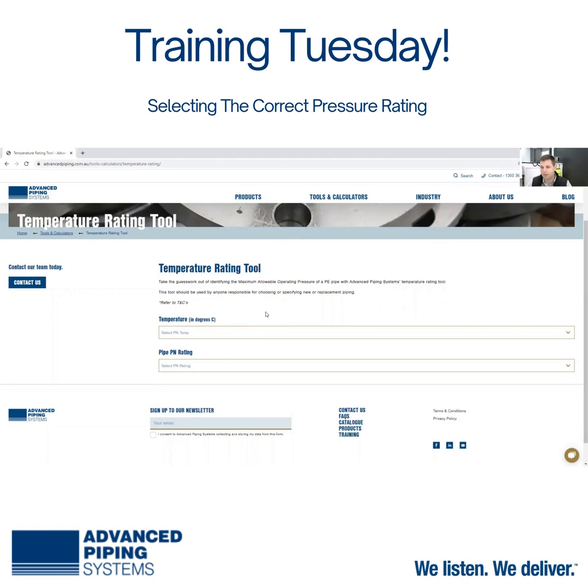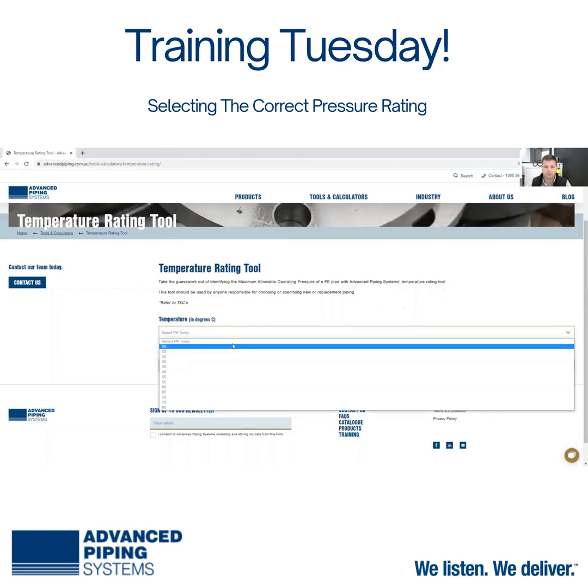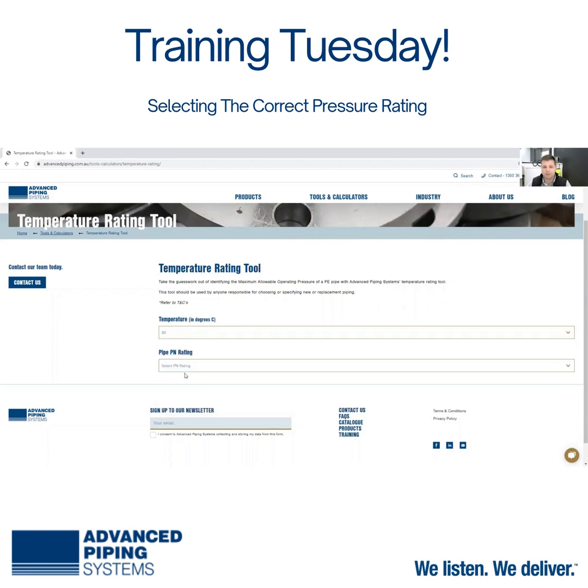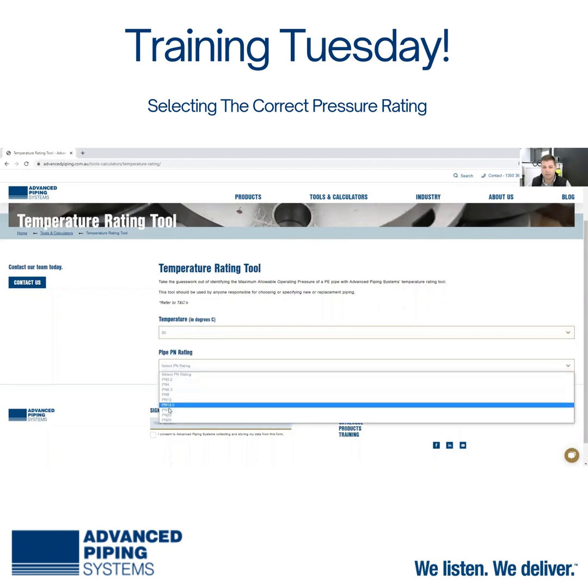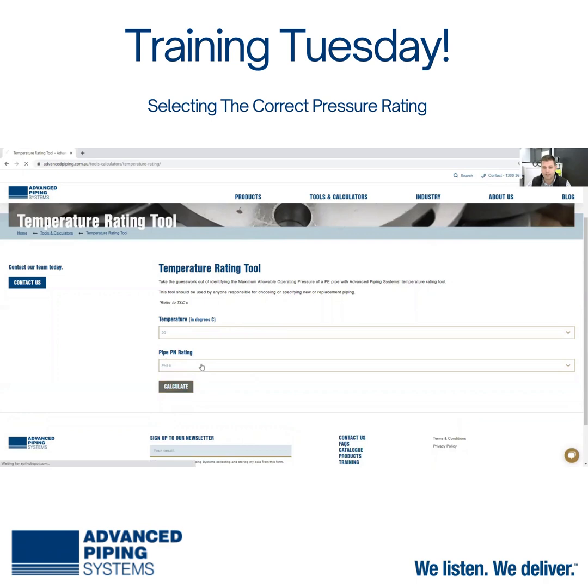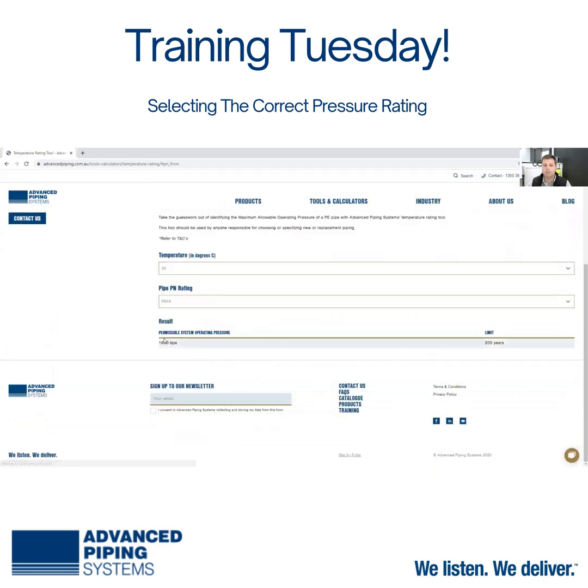If it's buried below ground and it's got water running through it constantly, it could stabilize at 20 degrees depending on where you are in the world. So if we select 20 degrees here under the temperature, and then we select the PN rating, which was PN16, and calculate it, we can see there that the permissible system operating pressure is 1600 kPa with a lifetime limit of 200 years. So that's about as long as anyone knows.